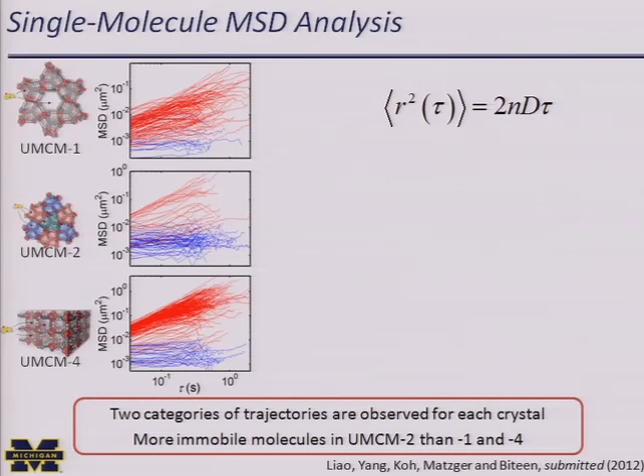Number 1, they are not homogeneous. And so in both cases, you see some red curves that have a positive slope. Those are mobile molecules, as well as blue curves that are pretty much flat sloped. Those are immobile molecules. Number 2, there's a different distribution. So UMCM1, for example, has many of these red tracks and few of the immobile tracks, whereas UMCM2 has many more immobilized tracks. And finally, if we look at the slope, it doesn't end up giving us n. It doesn't end up agreeing with 1 or 2 for 1D or 2D motion.